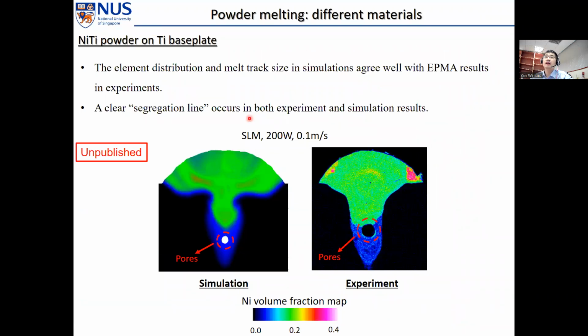Another case is nitinol powder on a titanium base plate. So these are two different materials. And for this keyhole regime, the chemical element distribution is very complex. You can see there's a keyhole pore here in the experiments, and then there will be a segregation line in the middle of the keyhole. You can see in our simulation, we also reproduce this phenomenon, including both the keyhole and the segregation line.